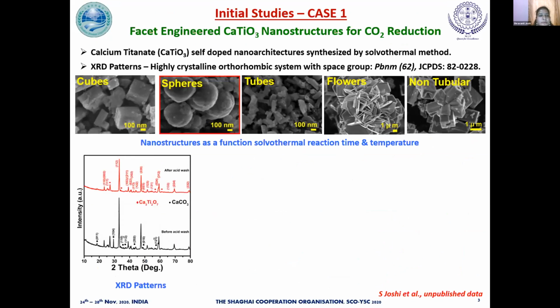Moving on, calcium titanate with a basic chemical formula ABO3 has a distorted perovskite structure and is an incipient ferroelectric and diamagnetic material. In first of its kind, exotic calcium titanate nano architectures were synthesized using solvothermal method with tailored facets and in situ self-doping mechanism. Now here if you see, the X-ray diffractogram reveals high crystallinity and orthorhombic crystal structure. Further, if you see the FESEM images, you can realize good quality tailored facets.